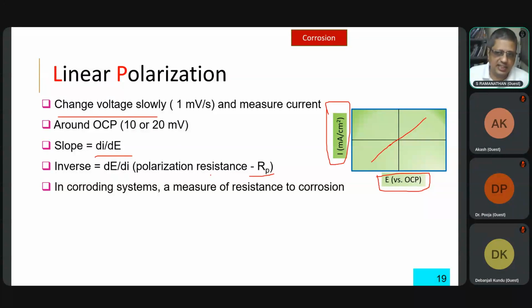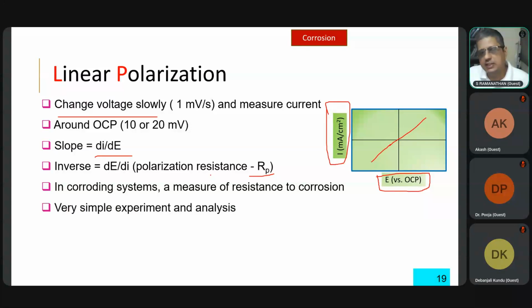So in a corroding system, this is a measure. This will not destroy the sample. You can measure this easily, and you'll get some idea whether it is resistant to corrosion or corrosion is happening at a high rate. So it's very simple in analysis, very simple to do the experiment, but you will also get limited information. Which means you will know whether it is corroding much or not, but if it's corroding, you won't know what is the process by which it happens, how can I reduce it, etc. If you want those, you need to do more sophisticated experiments.